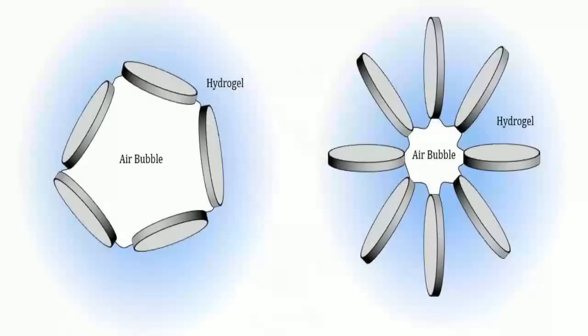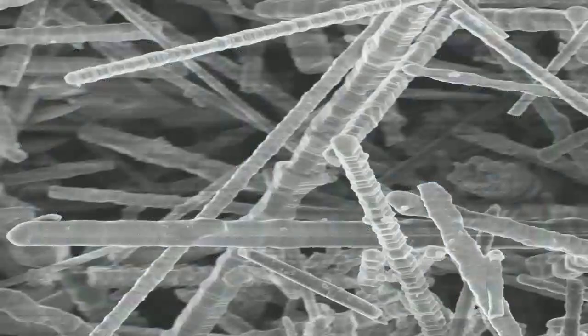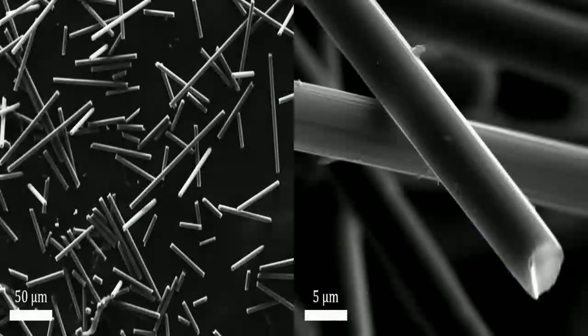They identified a few culprits. There's always some general residual porosity left after sintering, just tiny voids. But more importantly, they saw defects between the individual printed filaments, like the lines didn't perfectly merge everywhere. This could leave small voids or maybe trapped air, especially if the filament surfaces were a bit rough. Ah, the seams between the layers or lines. Precisely. They also noted some larger powder clumps or agglomerates in the paste itself that didn't break down.